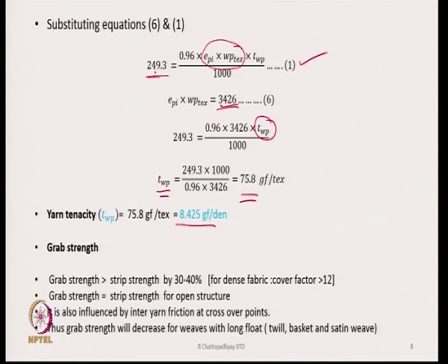Here we need to write a few more points, that is, grab strength generally is greater than strip strength by 30 to 40%.